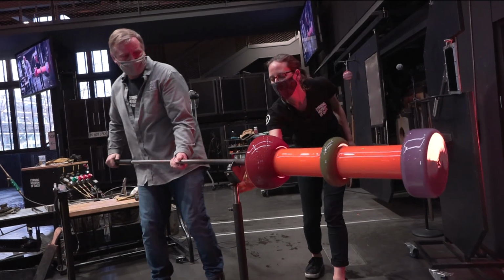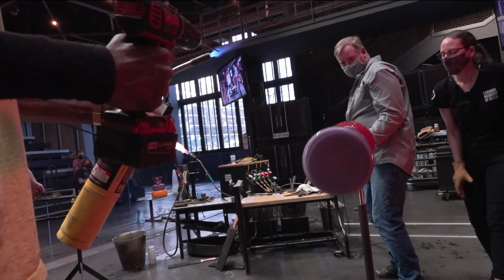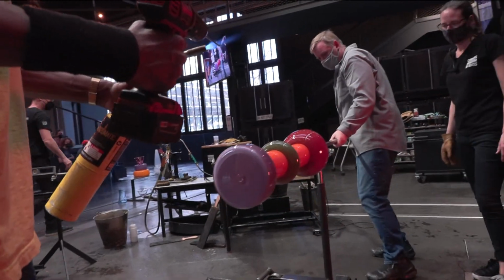The largest piece of glass in the museum's collection is the 200-inch disc that was cast here in Corning out of Pyrex for the mirror in the telescope at Mount Palomar, the Hale telescope. It weighs 20 tons, and it had to slowly cool, or anneal, for 11 months. The first attempt at that casting is up in the Innovations Gallery. You can check it out today.